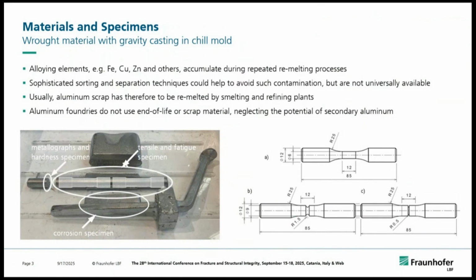So there are a lot of influences from melting, from refining, and what we did in this case was concentrating on gravity casting, which is produced in a chill mold. What we see on the left side is the chill mold, or the product, the casting at the end, produced in the chill mold, where we have the runner and the riser system of the casting system, and we removed some round specimens from this chill casting. We now concentrate in this presentation on unnotched specimens on the one side and 2 notch geometries on the other side, trying to see what is happening at the end with the fatigue strength, and what the results are under the different stress concentration factors.